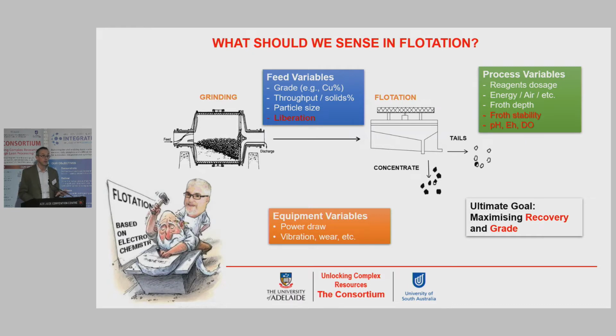Then we have process variables, where we measure the dosage of reagents, energy to the flotation cells, air flows, froth depth, and so many other things. And then some other relevant parameters, which is froth stability or characteristics of the froth, and mostly pulp chemistry, pH, EH, and DO.